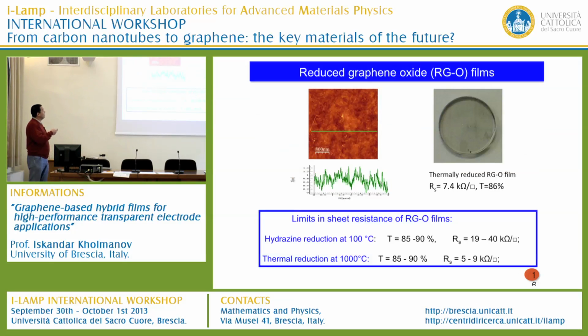The reduced graphene oxide films, by a simple method, by spin coating, dip coating, or drop casting, you can obtain a very smooth and continuous graphene oxide film. This is the reduced graphene oxide, reduced thermally on a quartz substrate. It's very transparent with a very homogeneous film morphology. But the problem is that we still have a very high sheet resistance, about 7.4 kilo ohm per square.